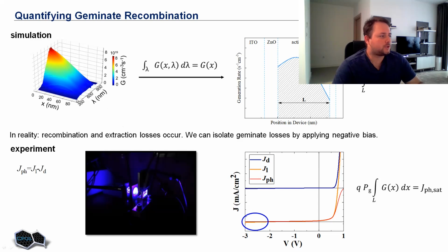We have this, let's say, two-dimensional distribution of generation rate along the thickness of the active layer and along the wavelengths. So what we do, we integrate over wavelengths to get the spatial distribution of generation rate caused by all wavelengths within the spectral range of photosensitivity. Once we have this distribution, we can integrate it over the thickness of the active layer, and times elementary charge, it will give us some theoretical short circuit current, meaning the maximum possible short circuit current, which doesn't take into account any losses caused by geminate or non-geminate extraction issues. So it assumes that we extract every single exciton which we generate in the active layer.